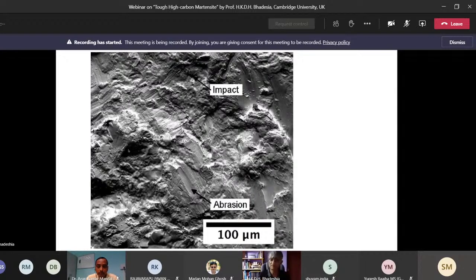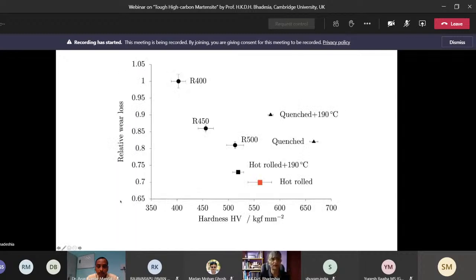We are very excited by these tests because if we look at the wear loss in this very severe test against hardness, our material outperforms any of the commercial alloys available, okay? So this is hot rolled condition, so without any tempering. If we take the same material and we simply quench it from the austenitizing temperature so that we have these equiaxed austenite grains which are large, then look, the wear rate increases dramatically, showing you directly the consequence of having these extremely fine martensite plates in the as hot rolled material. These will not be fine and will have a lower toughness, okay?